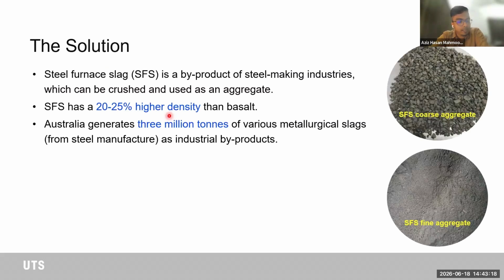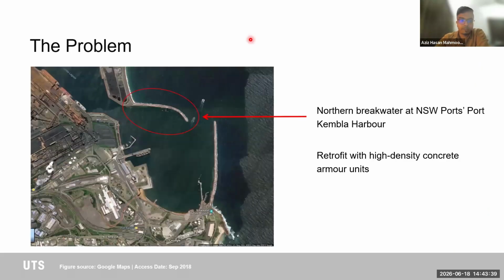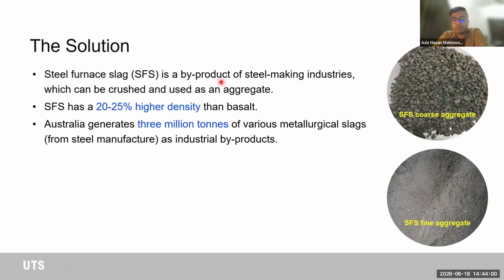Now, in order to increase the density of your concrete, the most appropriate way would be to substitute your coarse and fine aggregates, that is your stones and your sands, with materials that have a high density. The steel furnace slag, which is a byproduct of steel making, we've chosen that as the material for making our concrete. And if I may go back to the previous slide here, this site is about 2 hours south of Sydney, and about half an hour drive, we have Australian Steel Mills Services, which produce a lot of steel furnace slag. So this was a locally available material that we could integrate into making the concrete.